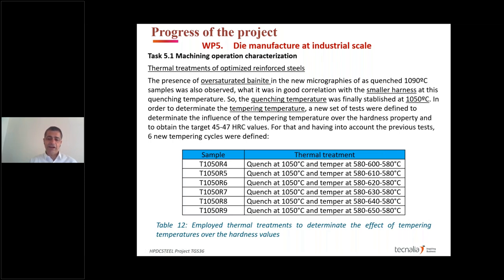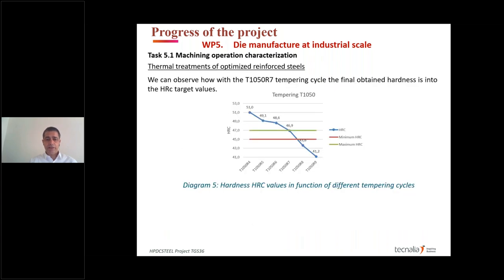So we defined an interval from 600 to 650 degrees in order to check the tempering process. We made the tempering process and we have these results. Increasing the tempering temperature, we decrease the hardness. So we have hardness values from 51 to 41 Rockwell C. If we wanted to work at around 45, we had to select the R7 or R8 thermal treatment.